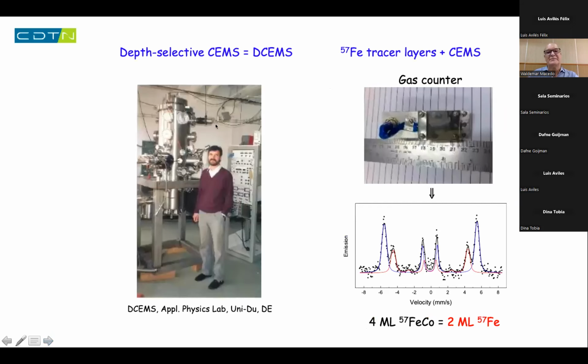And that means then you don't need a big analyzer like this. This is an analyzer I constructed in Germany a few years ago. You see, I still had hair at that time. But you can use, let's say, a very simple homemade gas counter. You can be sensitive to, let's say, this spectrum of 2 monolayers of iron 57 or 4 monolayers of an iron cobalt alloy.